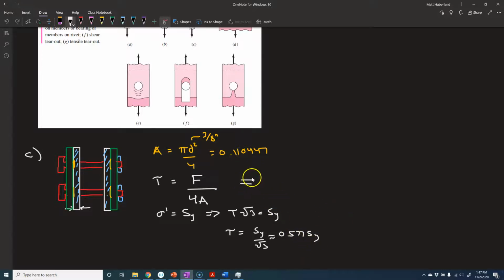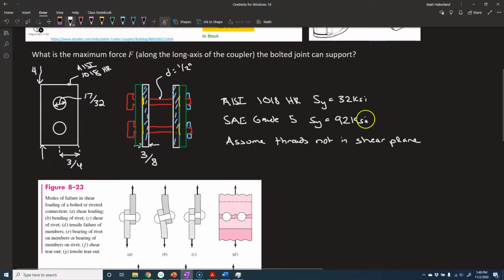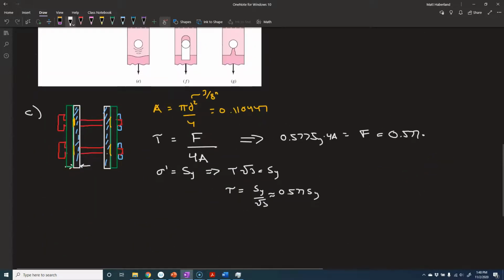So this means at yield, tau can get up as high as 0.577 SY. The force at yield is such that this is true. We can multiply both sides of the equation by 4a, and this is going to be the force at which the bolts will all yield at the same time. So let's plug in numbers. We've got 0.577. The yield strength that we're talking about here is that of the bolts, because we're talking about yielding the bolts in shear, 92 KSI, times 4 times our area of 0.11. That is 23.452 kips. And these bolts will all yield.